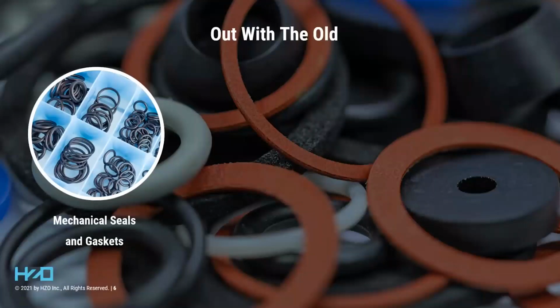Adhesives and form-in-place gaskets eventually lose adhesion. They soften in heat and are not effective after disassembly and repair. Gaskets and mechanical enclosures can crack, age, loosen over time. They suffer from temperature fluctuations, so they no longer seal as well as they did when they were first put together. And moisture and gases can eventually get in because most of these things are typically polymers or rubbers in nature. All of those breathe slightly. You're going to have gas ingress, you're going to have moisture ingress, which eventually collects inside the device.